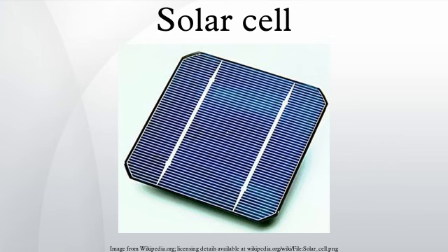GaAs thin film cells. The Dutch Radboud University Nijmegen made a single-junction GaAs cell that reached 25.8% in August 2008, using a 4 micrometer thick GaAs layer transferred from a wafer-based cell to glass or plastic film. Recently, this increased to 28.8%. The efficiency was attributed to high-quality GaAs epitaxial growth, surface passivation by the AlGaAs and the promotion of photon recycling.